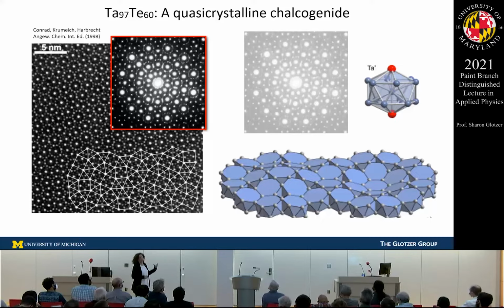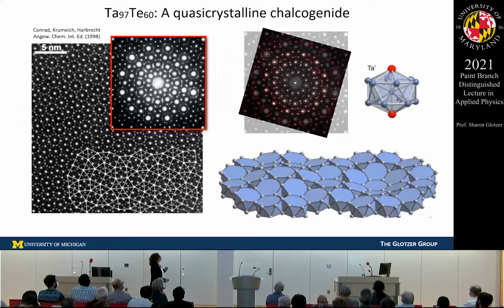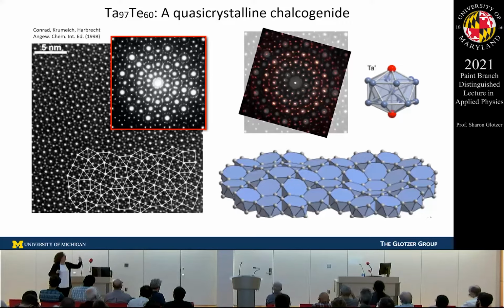One of the ways you can see if you have a quasicrystal is you draw these tiling patterns on top, and it helps you figure out what kind of crystal you have. And you could see that there's this layer that you could take out of this particular quasicrystal where you could see these 12-member rings of atoms. Of course, it's different because they're atoms, they're not solid particles. But if you were to compare the diffraction patterns, they're identical. I should say, if you scatter off of the centers, the centroids of the tetrahedra, then you get identical patterns.